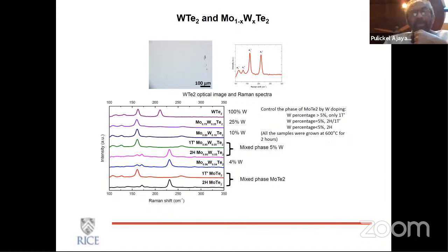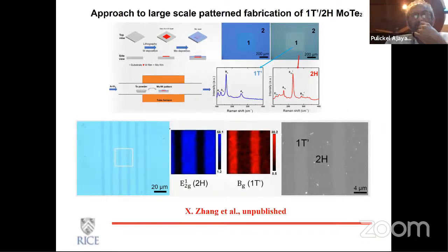So we thought that it would be an interesting way to create these periodic structures by creating a sub-layer of tungsten first and then growing the molybdenum telluride, so that the tungsten would diffuse and then create these metallic 1T. So by this technique, we were actually able to make large area of repeating patterns of 1T prime and 2H by simply having these underlying tungsten regions that create this diffuse layer of molybdenum telluride, which forms the 1T prime. So one could do all kinds of tricks like this to actually get these periodic structures and in-plane junctions that you want, which is very, very interesting.